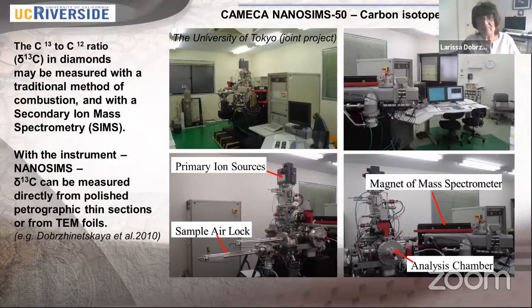So new technology came, and we started to use at that time the NanoSIMS. What does NanoSIMS mean? Everybody knows SIMS, okay? However, NanoSIMS has a very, very tiny beam, 50 nanometers in diameter. It means that this beam can penetrate a very thin sample. So you can go to the NanoSIMS instrument to study carbon isotopes with a foil which you prepare for transmission electron microscopy. We did this in collaboration with the University of Tokyo. At that time, that was one of three NanoSIMS available in the whole world. It was the beginning of this era.